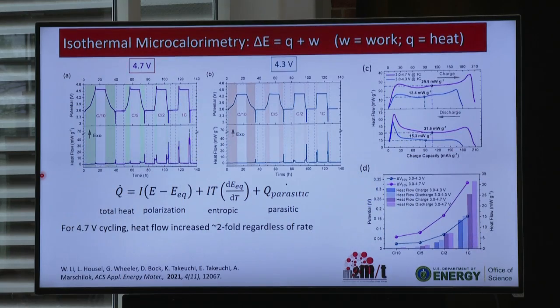And we studied, again, NMC batteries that were charging to 4.7 or 4.3. No question about it, we looked at five different cycles at five different current levels. The batteries that were charged at 4.7 dissipate much more heat. It's about a factor of two higher compared to the batteries that are charged to 4.3. So for that 20% gain in capacity, we're dissipating about two times the level of heat. That gives you some sense that there's a lot going on when you change the charge voltage.